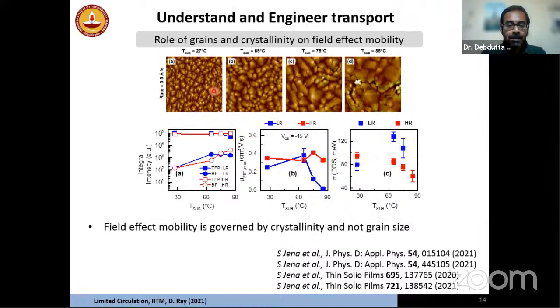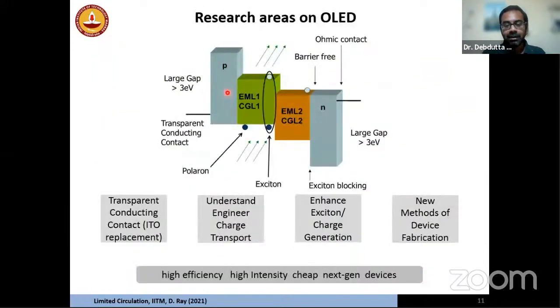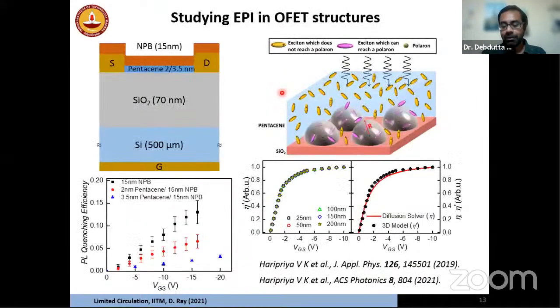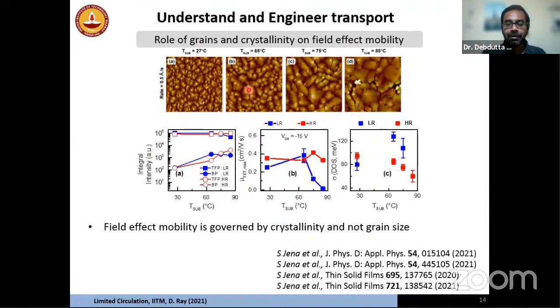All right. Then we also try to look at carrier transport. So for example, you can engineer carrier transport in these materials. Transport is a big issue because, if I go back to the screen, you need to have these holes move nicely, and these electrons move nicely, right? So what we need to do is engineer transport, and this you can do by changing, for example, the morphology, right? So here I'm showing you different morphologies grown. The way you grow defines what kind of morphology you end up with. And then we try to study how this morphology, the crystallinity, affects your mobility, right?